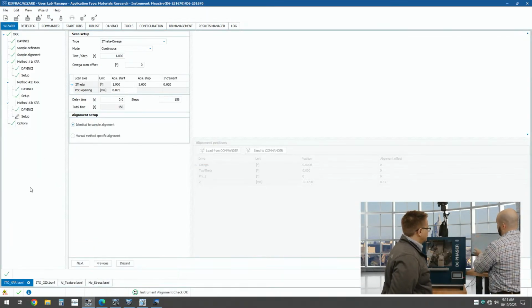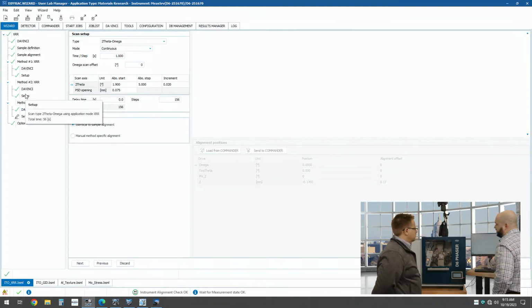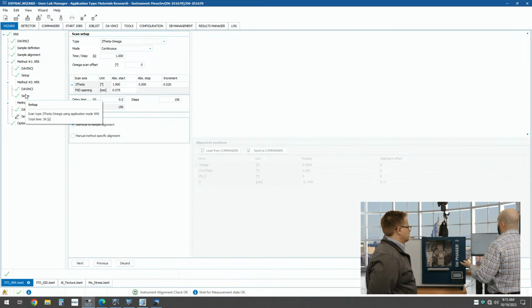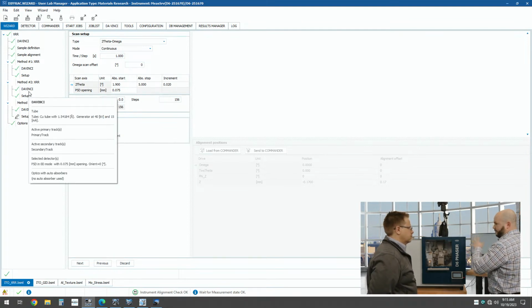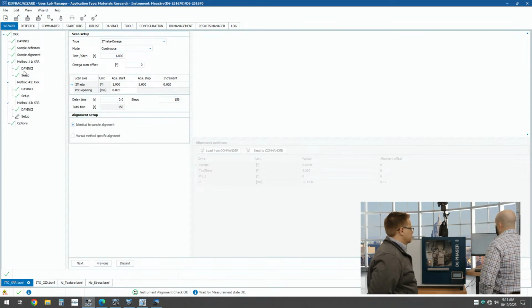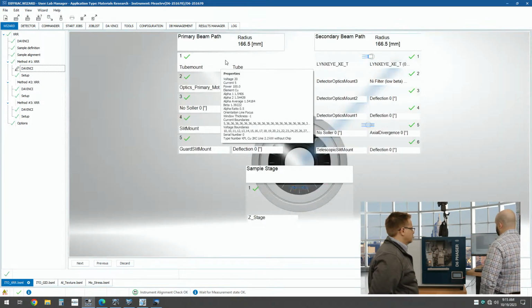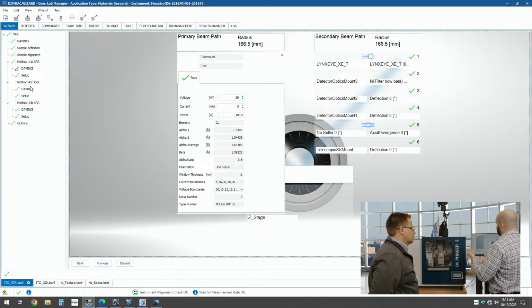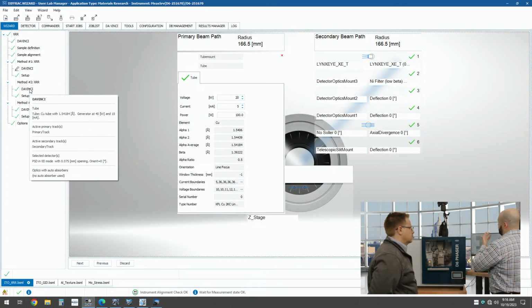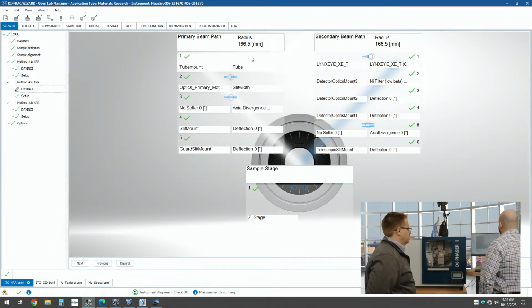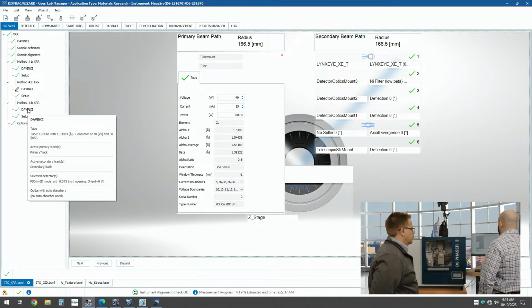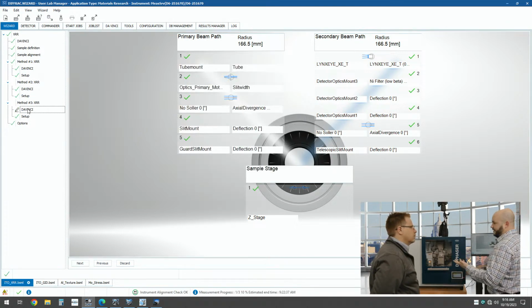This measurement I have defined in our wizard for planning. We commonly use that to plan our measurements. And so I have 3 different segments here. Instead of using a copper absorber to keep the detector linear at those direct beam conditions, I'm basically just ramping the power of the tube up as the measurement proceeds in these segments. So as you go deeper and deeper into the sample, you lose more and more X-rays, right? Yep. So you can see I start off at pretty much standby current and voltage, and then I ramp up. And so this basically eliminates the need for any copper absorbers or things like that to get nice linear measurements.